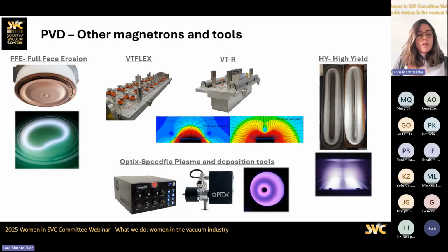So just to give an idea of how diverse our products are in the PVD world, and that makes it interesting, is, for example, this one, the full face erosion, where the magnets are rotating behind the target, so you have this type of erosion. Then you have VTFLEX, where we can go so far as creating different magnetic paths to adjust for different uniformity in a single magnetron. Then we could have any other different magnetic options, like for example this one, that you can rotate and convert from being unbalanced to more balanced during the deposition. High yield for precious materials. As you can see here, you can use much more of the material.